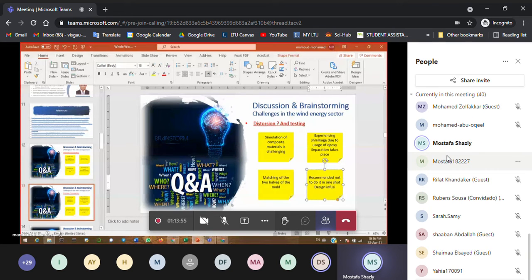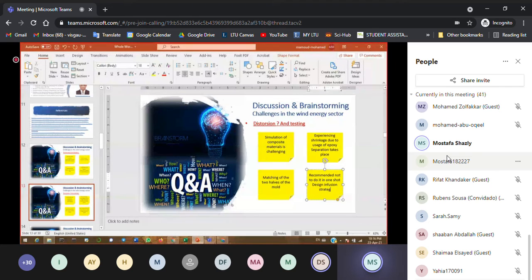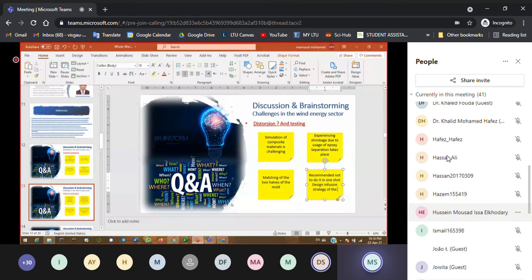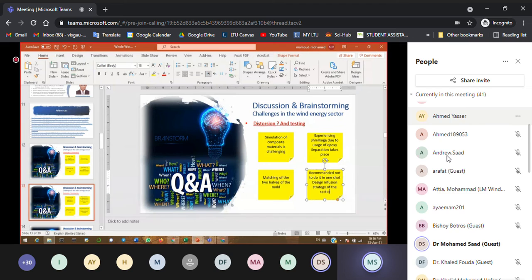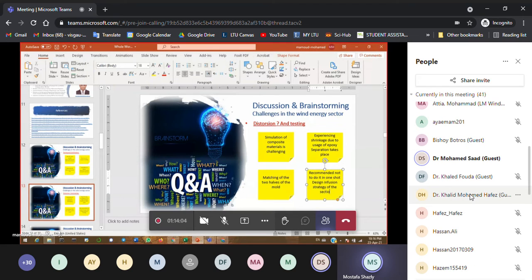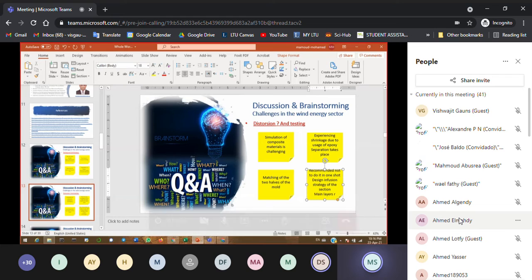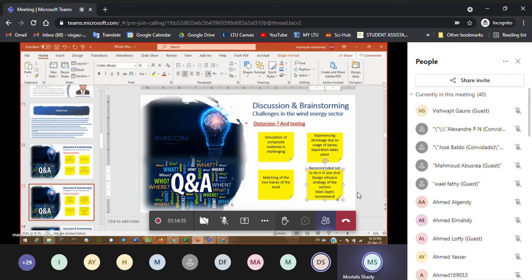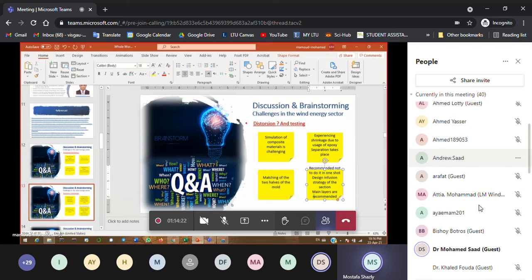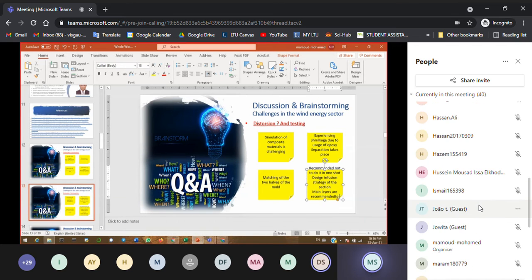So now, if I go back and do the infusion process, I will just do the infusion for the main layers, which span the full length of the blade. And then I'll do the rest of the layers to build up the section of the root, just to avoid such a high shrinkage effect at the root. Yes, but you're right. Shrinkage is one of the problems with the epoxy. Exactly. Thanks so much.